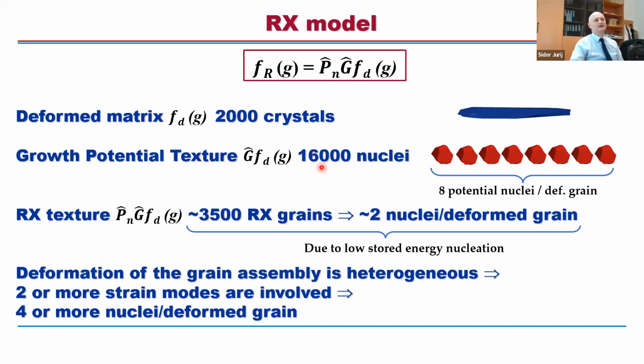We will have immediately 16,000 crystals, so 8 potential nuclei per deformed grain. However, when you apply nucleation operators, I will end up with approximately 3,500 grains. So it depends from case to case. So roughly 1.7, I would say 2 nuclei per deformed grain. So with this approach, we were able to reproduce our recrystallization texture, right? We have this selection, only 2 out of 8, due to low stored energy nucleation. So some grains, it depends on the orientation, will produce more nuclei and others less, but on average 2.